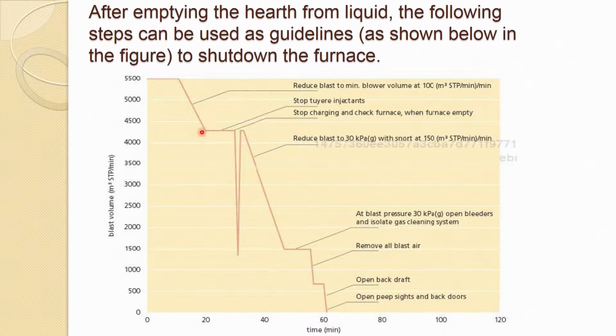Then somewhere after half an hour you stop the tuyere injectant, if you are having oil fuel or gaseous fuel or PCI, anything, and then you stop that one. Stop charging and check the furnace when the furnace is empty. When the furnace is empty, then almost after